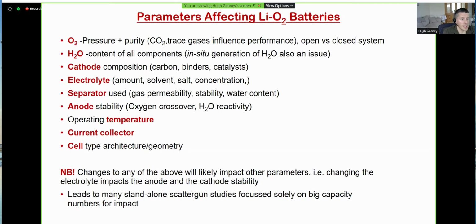Again, you can imagine that's going to influence the gas permeability and the stability and water content of that. The anode stability, so we're talking about a lithium metal anode. If you have oxygen crossover, you can start to get reactions at the lithium side, and also the water reactivity as well. Obviously, the operating temperature, the current collector, and the cell type and architecture. So the point here is that any change to the above parameters is going to completely change how the battery performs. So what has happened to date is we have had a lot of these standalone scattergun studies where people will just try and get the biggest capacity numbers that they can get to maximize their impact. But then there are all of these open mechanistic questions still out there.